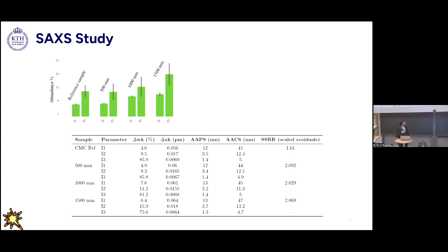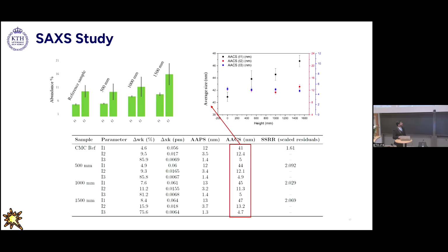If you look at the particle size distribution for I1 and I2, which belongs to particle sizes of roughly 5 nanometers to 15 nanometers, you will see increased abundance. And it's not coming from anywhere else. It's just the breaking down of the bigger, higher order particles into these particles. Also, if you look at the AACS, average apparent cavity size, you can see an increment in the cavity size of roughly 40 nanometer cavities.